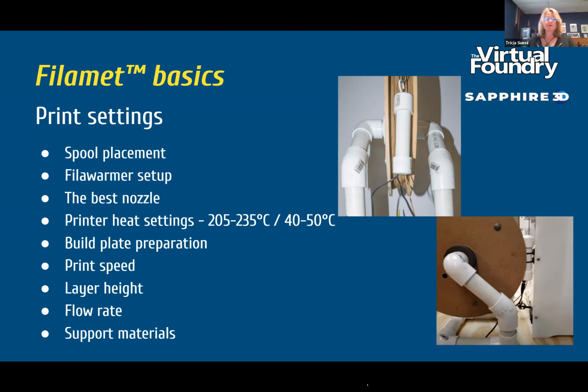We mentioned the nozzle earlier. You're going to use a stainless or hardened steel nozzle sized at 0.6 or 0.8 millimeter. The harder nozzle is important. A brass nozzle will work, but it will wear down pretty quickly, and then your print will begin to fail. So the stainless or hardened steel nozzle will stand up to the materials much longer than that brass would. And we recommend that little bit larger size at 0.6 or 0.8 just to help with the printing process.